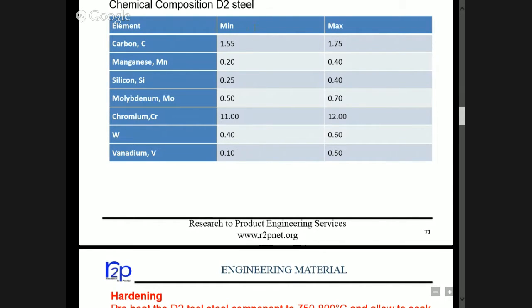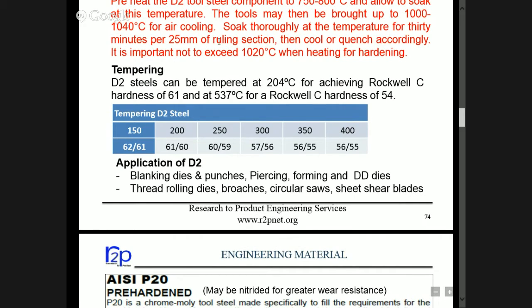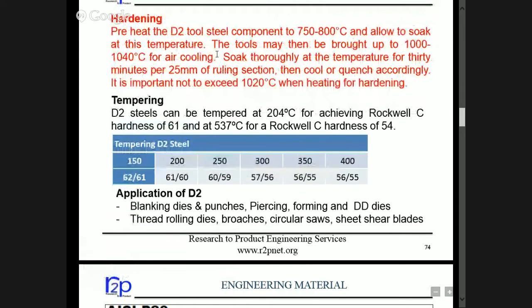Here is the chemical composition of D2 steel; you see the chromium is very high. And here is the hardening cycle for D2. After soaking at 750 to 800 degrees centigrade, it is taken to 1040, stabilized at that temperature, and then quenched accordingly. For tempering, it is tempered at 204 degrees centigrade, achieving Rockwell hardness 61.